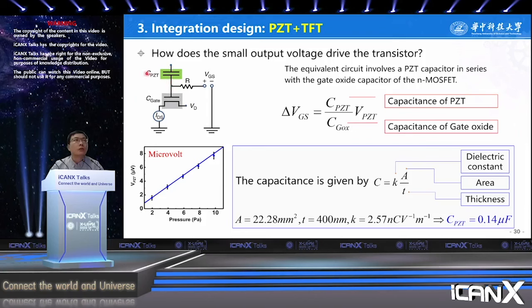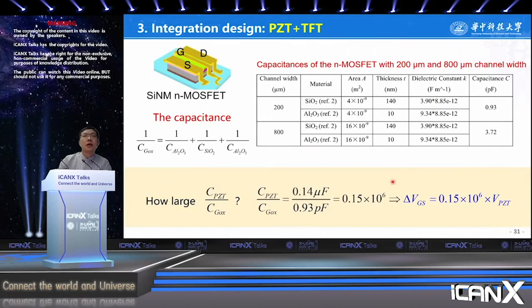The voltage division factor equals the ratio of the capacitances, so we can get two totally different voltages across the two capacitors. Based on the capacitor equation, we can calculate the PZT capacitance, which is equal to this one. It's in microfarads. The next issue is how to calculate the capacitance of the gate oxide part of the TFT. The TFT is a multilayer thin film structure with 3 dielectric layers, and the capacitance can be calculated with this equation. The material and thickness of each layer are listed in the table, including the size, thickness, and dielectric constants. Then one can get the capacitance of the TFT.